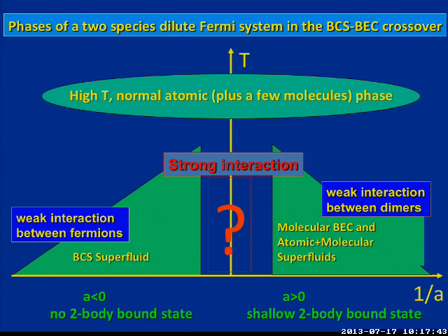The problem which we have now is the following. We can vary the scattering length, and it's convenient to study the problem as the inverse scattering length. This is the unitary regime, it will be somewhere here. If we have slightly attractive interaction, we get the BCS. This is what you just mentioned, and that's known. You get slightly repulsive, but this is also attraction, because how do you get that? You increase the interaction, you form a bound state. At that point, the scattering length is infinite. You increase the interaction further, the bound state goes down, but the scattering length becomes positive. So at this point, you form dimers.